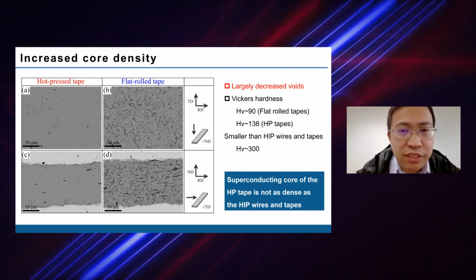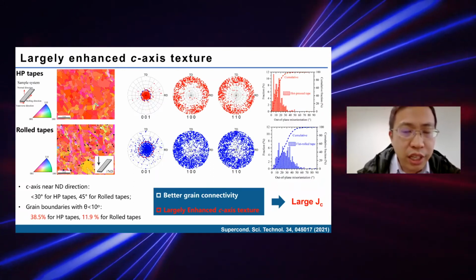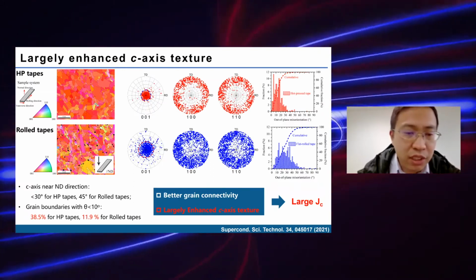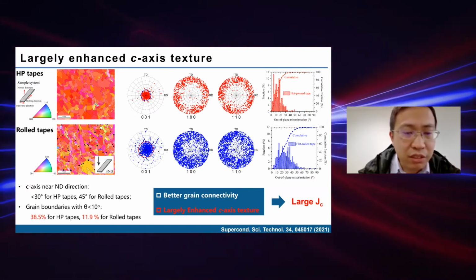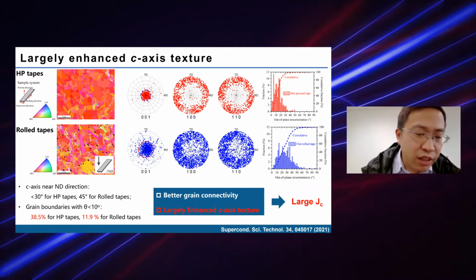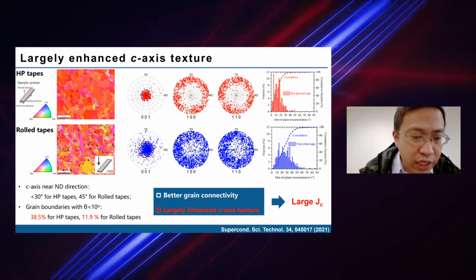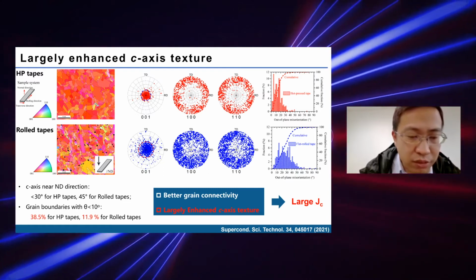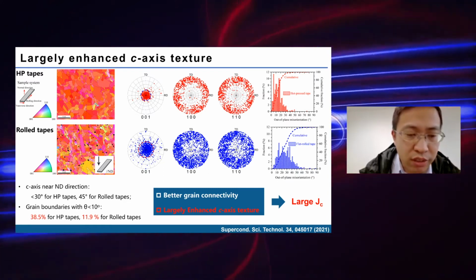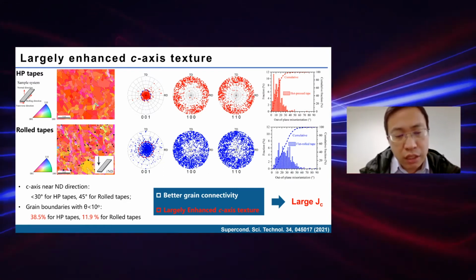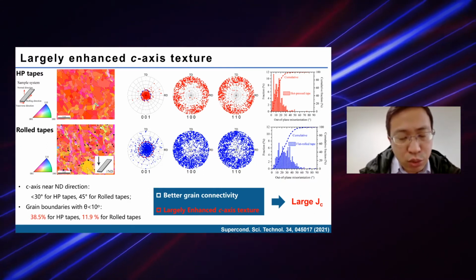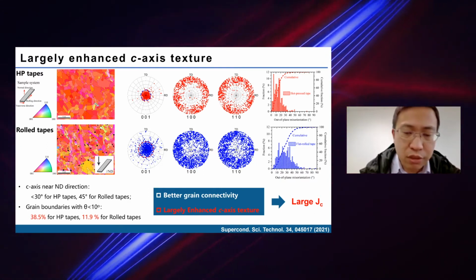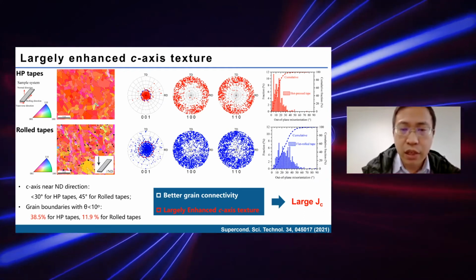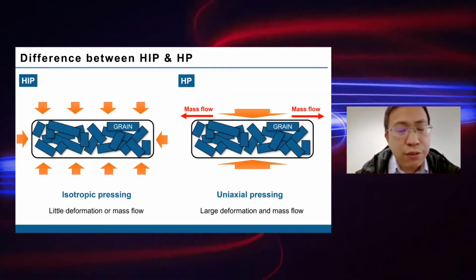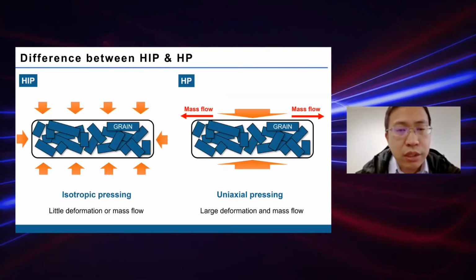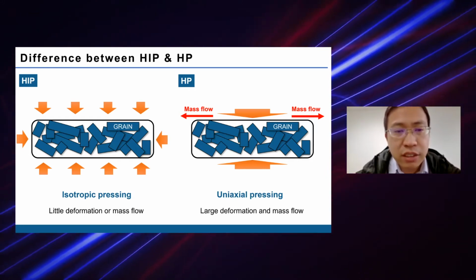On the contrary, the c-axis texture is largely enhanced in the hot press tapes, as evidenced by the EBSD results. There are 38% of the grain boundaries with orientation smaller than 10 degrees. However, there is only 12% for the roll tapes. So what is the difference between HIP and hot pressing?